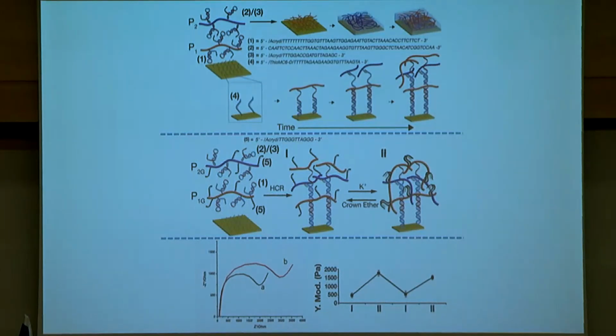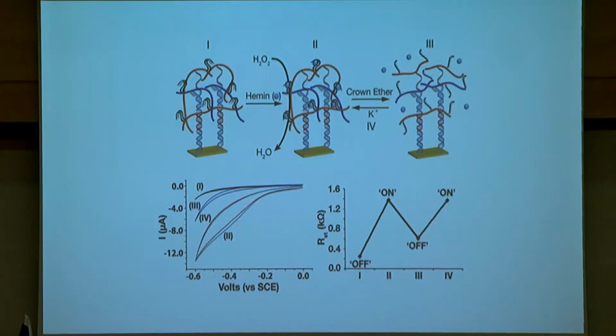You can see here, for example, microindentation experiments that really measure the Young modulus of the hydrogel in the presence and absence of the G quadruplex. You can switch it back and forth. Once you have this hydrogel on the electrode and control the stiffness of the hydrogel, you are able to go one step further and make a switchable electrocatalytic electrode.